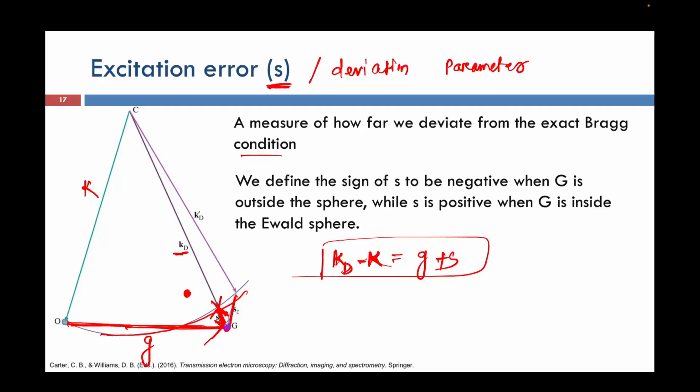So instead of points, we consider an elongated object. The Ewald sphere is going through, and my elongated object is still touching the Ewald sphere. Although the Ewald sphere is not completely intersecting my elongated object, I am still getting weak diffraction.